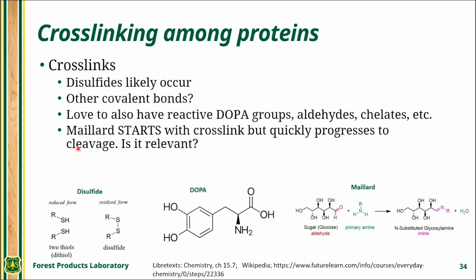Maillard reactions are very commonly mentioned in the literature and used as an explanation for why you develop strength. And I want to point out that Maillard starts with a cross-linking reaction here, but it quickly progresses to cleavage. And so I am not convinced that it's actually relevant for protein adhesives because this is really a transient state. And if you get a lot of Maillard, you probably have a lot of it going beyond into the cleavage state, so it's not helpful anymore.